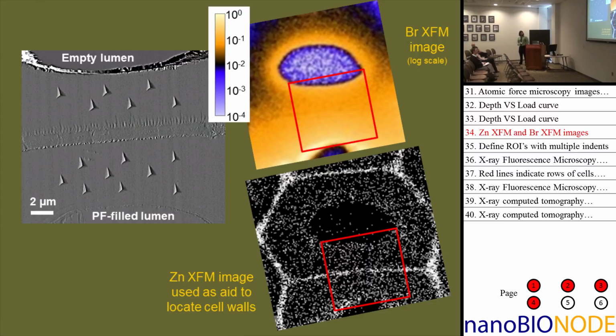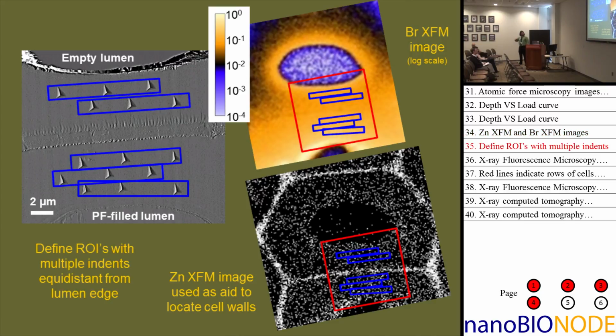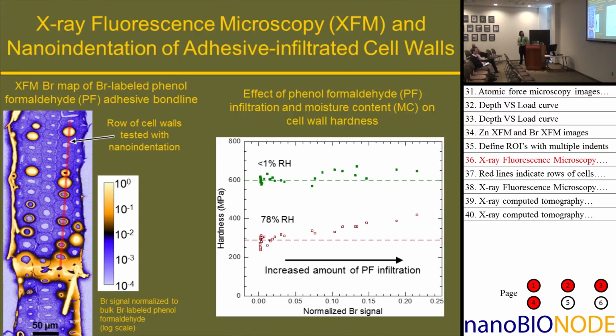Then we were able to find these exact same cell walls back on the bromine X-ray fluorescence microscopy image. And just to give you an idea of the sensitivity of this technique, these are the trace amounts of zinc that are inside the wood cell wall structure, and there's more zinc in the middle lamella. So we can use those maps to help us identify where these cells are in the bromine map. And then we basically just defined ROIs with multiple nanoindents, and then took the bromine concentration from there.